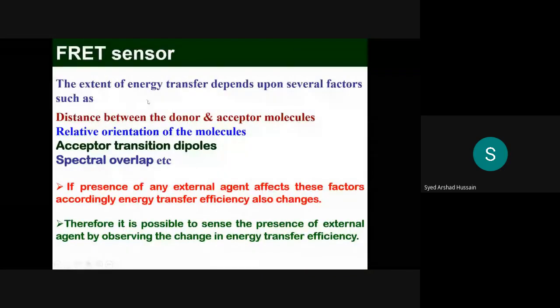The extent of energy transfer depends upon several factors. For example, the distance between the donor and acceptor, relative orientation of the molecules, acceptor transition dipoles, and also spectral overlap. If the presence of any external agents affects these factors, then the extent of energy transfer from donor to acceptor changes. And in the other way, by observing the change in energy transfer efficiency, one can have an idea about the presence of external agents. So this gives you an idea that one can have an optical sensor using this process.